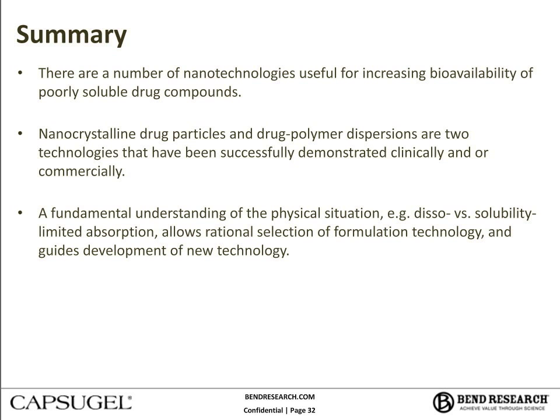One is filtration through membranes of various sizes, so from 1 micron to 0.45, 0.2 micron filters, as well as the smaller membranes that were mentioned. For the data we showed, those actually went through the, say, 100,000 molecular weight cutoff filter membranes that are associated with centrifugation. So there are a number of methods of separating freely dissolved drug from drug and particles, and so care needs to be taken to do that, to verify that one knows what's being measured. So good question.